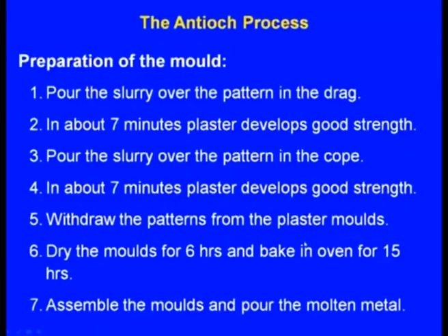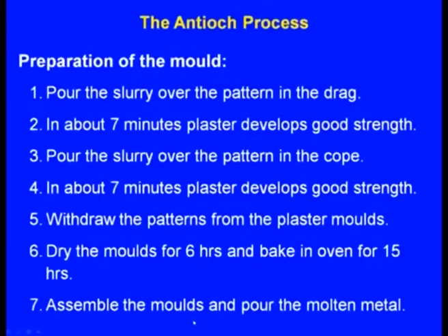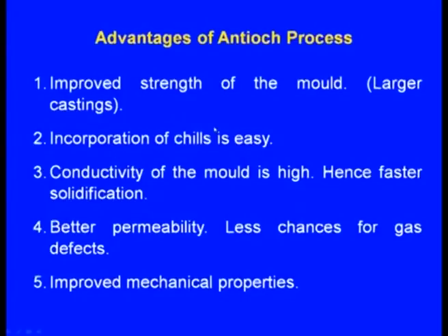Next one, withdraw the patterns from the plaster molds as usual. Now dry the molds for 6 hours and bake in oven for 15 hours. Assemble the molds and pour the molten metal. Now what are the advantages of the Antioch process? Improved strength of the mold.